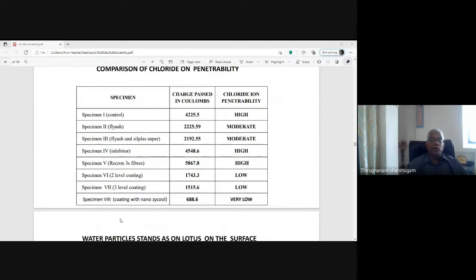Our experiment shows that for the control specimen, the total charge passed is about 4000. That is, high penetrability is there. It is a control concrete. If admixture is used, slightly less, moderate penetrability, 2000. So if mineral admixture and superplasticizer or chemical admixtures are used, more or less the same thing, 2000, moderate penetrability. If corrosion inhibitor is used, it will not give any effect on chloride ion penetrability. It is only for corrosion resistance, not chloride ion penetration. So once again, high penetrability is there.